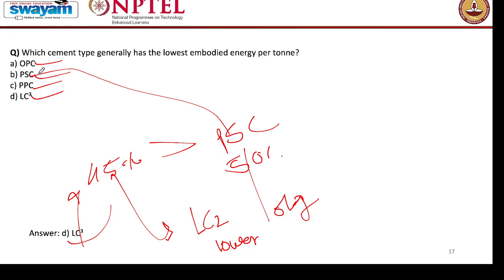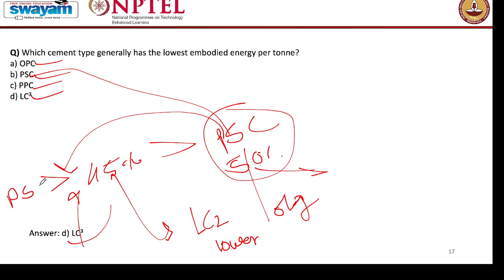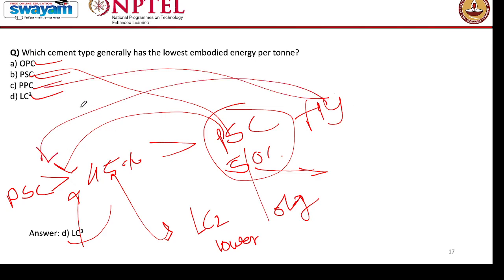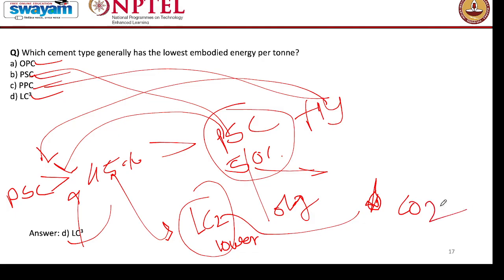Okay, and then there is a but. When we increase the PSC amount, the slag amount, to more than 50%, then the CO2 footprint of PSC will become even less than LC3. Fly ash is also a similar case. If we increase a high amount of fly ash, then that will have lower CO2 emission. Because for LC2 production, some amount of heat is required, which also generates CO2, right? Okay. That's why this has to be carefully answered.